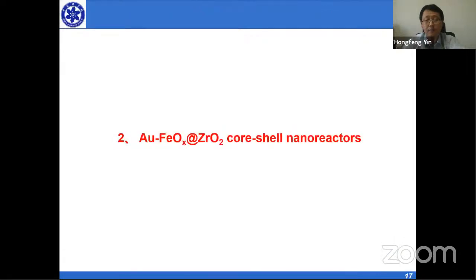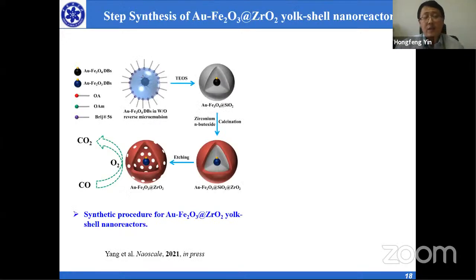Here we come to the gold iron nanoparticle with zirconia as the shell. If we replace the shell with zirconia, this synthesis is stepwise, not the one-pot synthesis. We first synthesize the gold iron nanocomposite, and then by introducing the silica precursor, we form this structure, and then we introduce a zirconia precursor. So it will form a zirconia shell on the surface. Then by etching, we remove the silica. Then we finally have this gold iron core and zirconia shell nanoreactor.